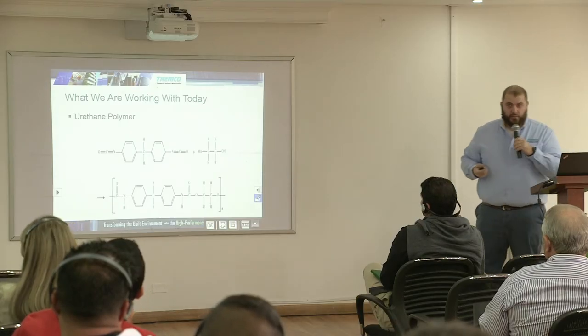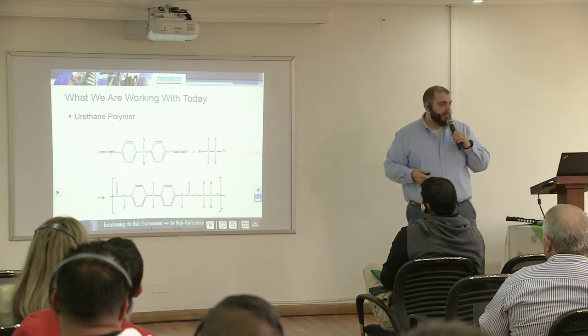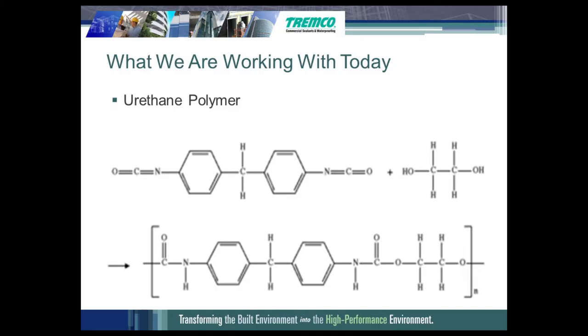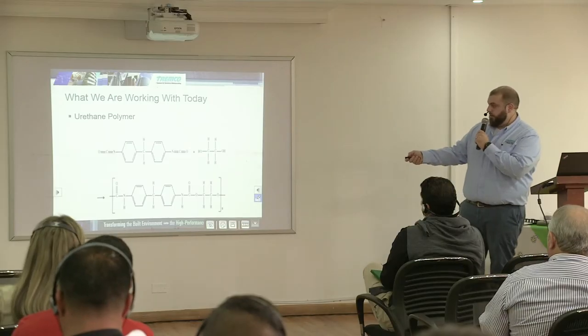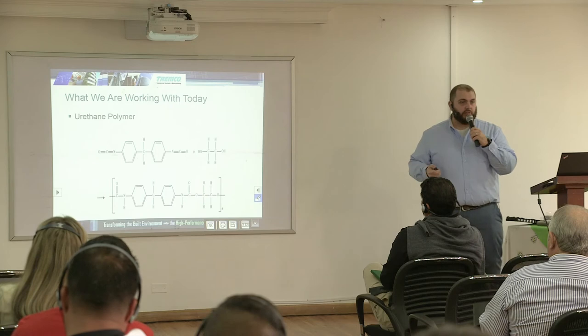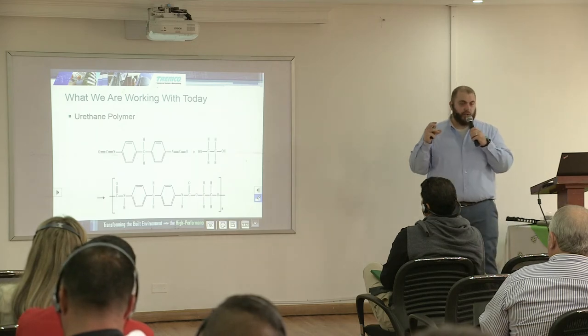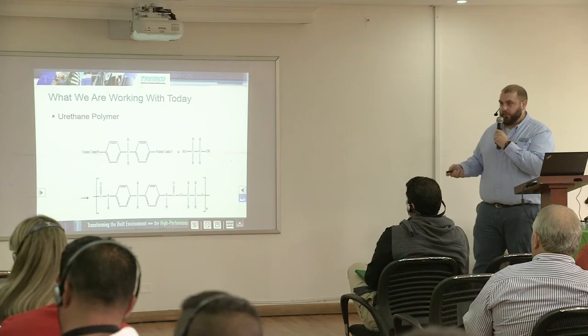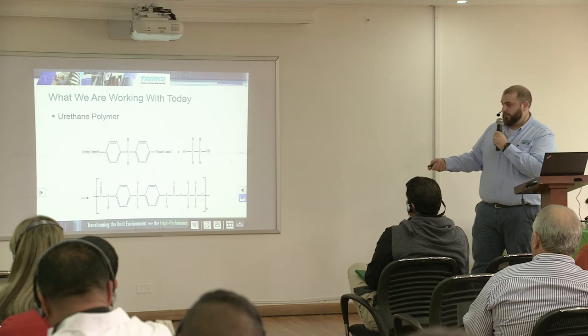The first that you use quite a bit, to my knowledge, is the urethane sealant. That is composed of a polyol and an isocyanate. You have both of these molecules in the same tube. If you have our Dymonic 100 or our Vulcan 45 SSL, they're in the same tube. You then have a blocking group that sits on the end of the polymer and interacts with the atmospheric moisture. That atmospheric moisture reacts with the blocking group and vacates it from the system, freeing up the active point for the polyol and the isocyanate to bond to each other. Here's just a simple example of what happens.